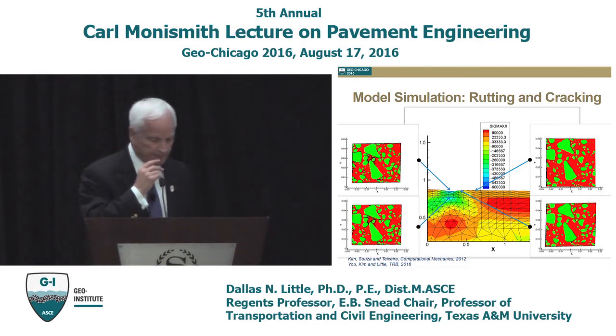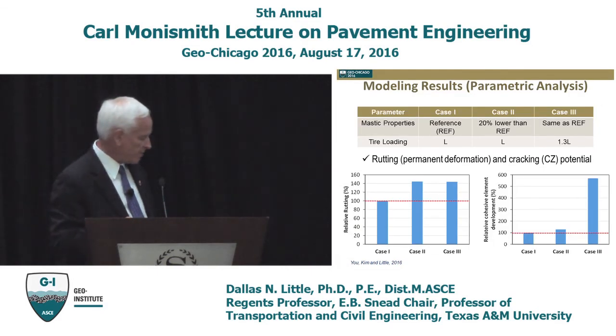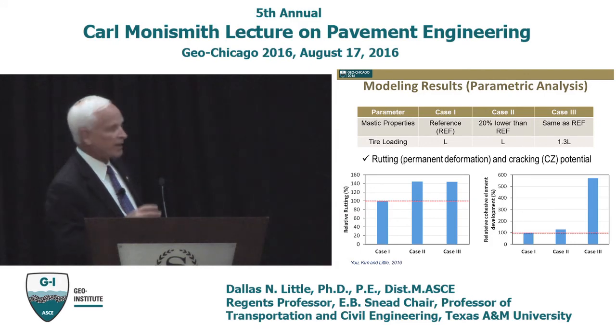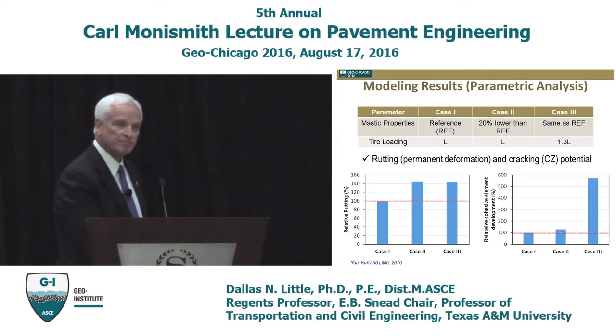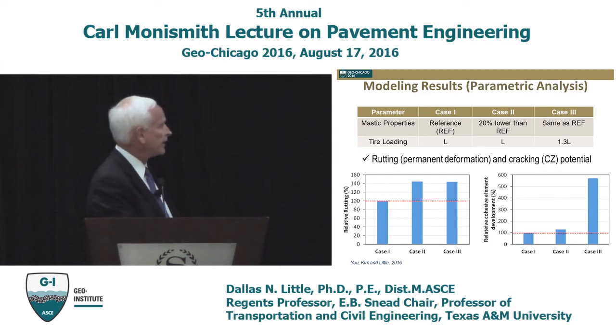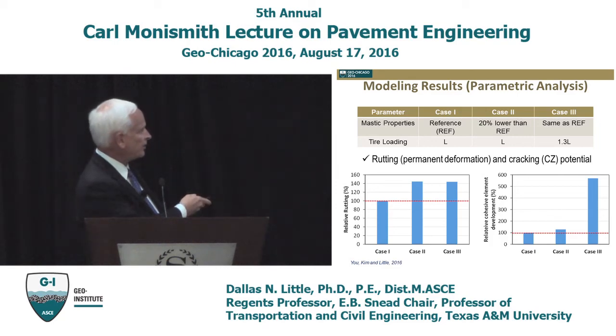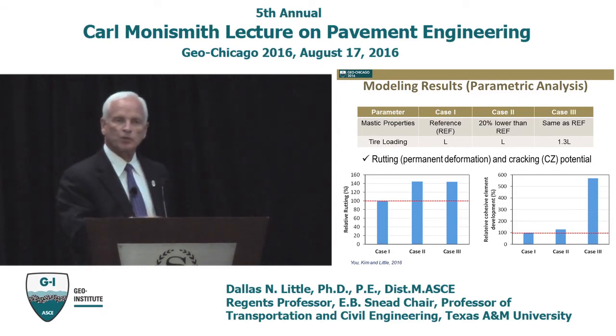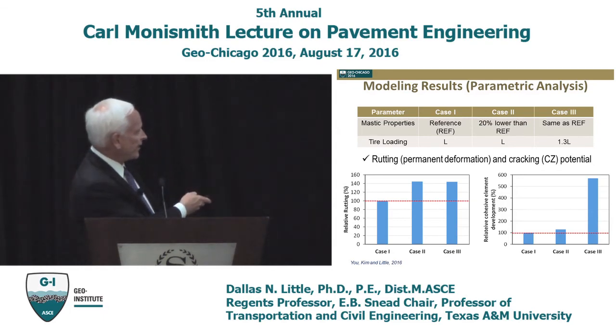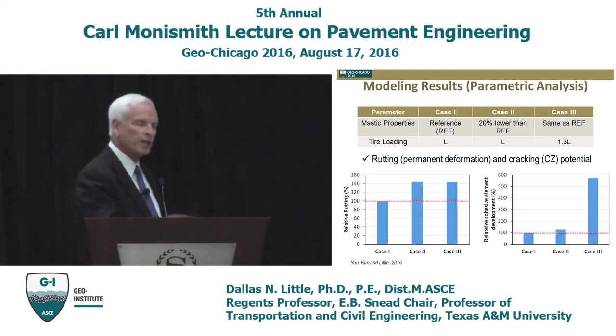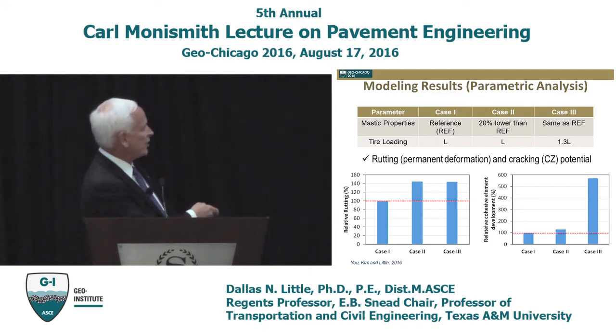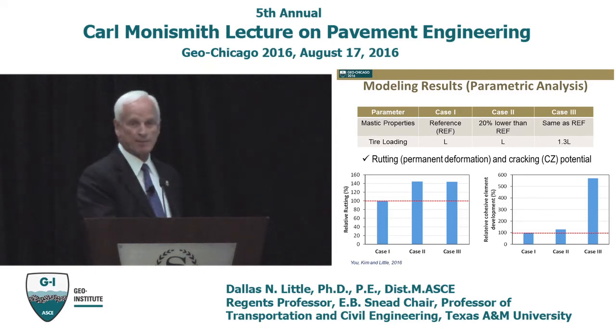Well, I had one other component there. In this paper that Professor Kim prepared, he used this approach, the coupling between the micromechanical mixture scale and the global scale, and he did a simple parametric study. He said, okay, case 1 is the standard reference mastic. Case 3 is going to be the standard reference mastic. Case 2, I'm going to reduce the mastic properties by 20%. Down here under tire loading, I'm going to have a standard tire load for cases 1 and 2. In case 3, I'm going to up it 30%. And then he evaluated, using this approach, relative rutting and relative cohesive element damage.